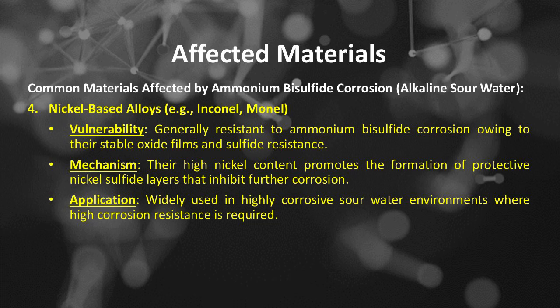Common materials affected by ammonium bisulfide corrosion or alkaline sour water, number 4, is nickel-based alloys such as Inconel, Monel. The vulnerability of nickel-based alloys: generally resistant to ammonium bisulfide corrosion owing to their stable oxide films and sulfide resistance. The mechanism: their high nickel content promotes the formation of protective nickel sulfide layers that inhibit further corrosion. The application: widely used in highly corrosive sour water environments where high corrosion resistance is required.